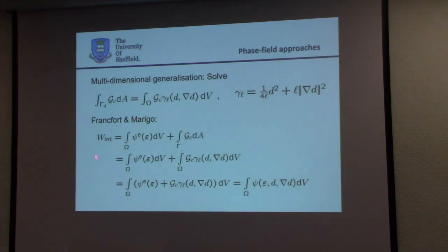Now, what is the specific application to fracture, and in fact to brittle fracture? Bourdin, Francfort and Marigo have said, okay, we look at the total energy of a body, and this is composed of the elastic energy in the body, plus the fracture toughness integrated over the crack length.